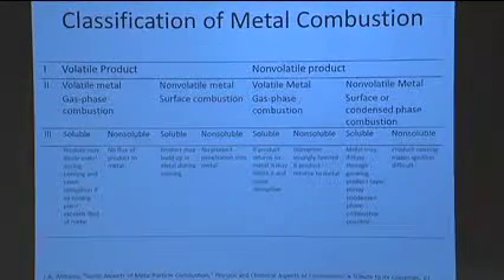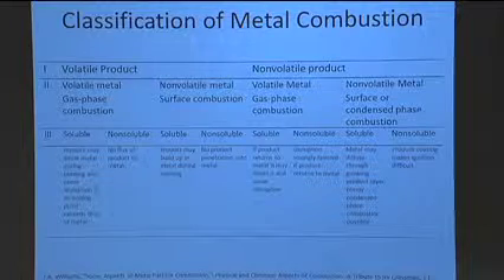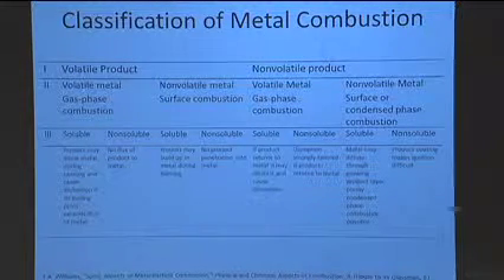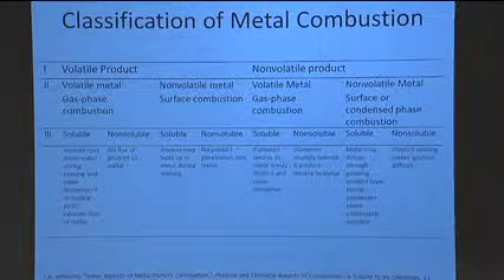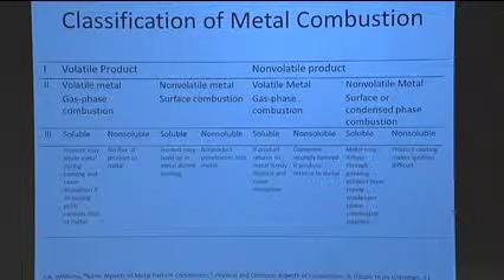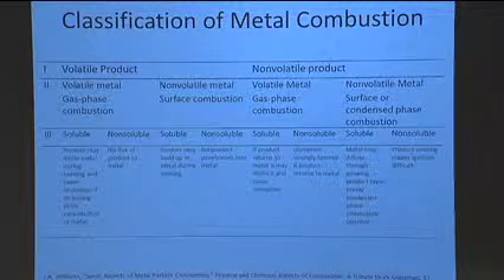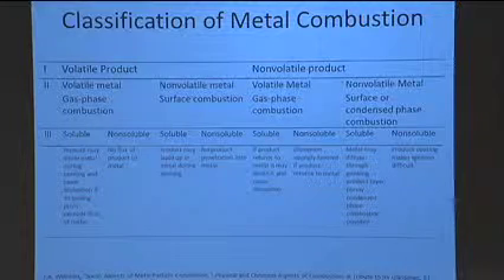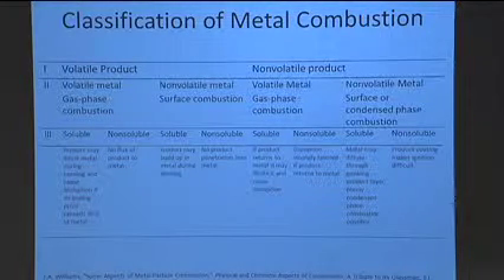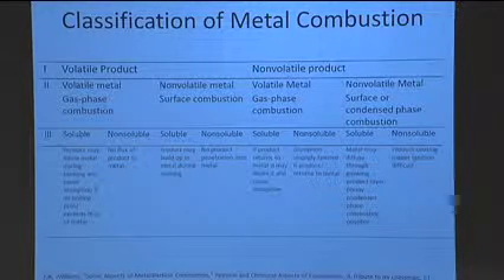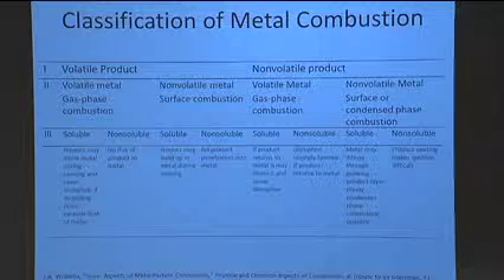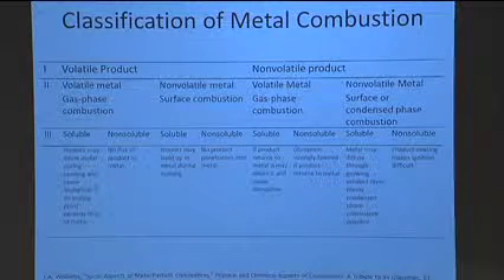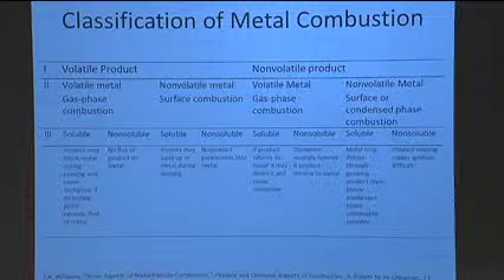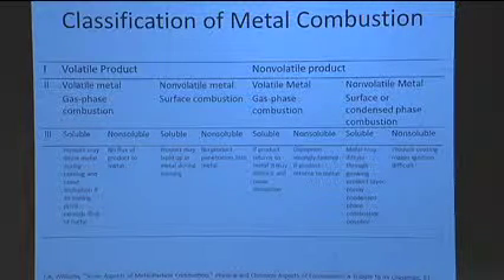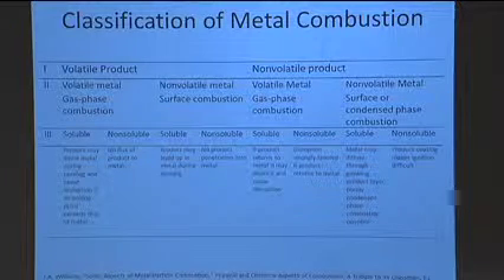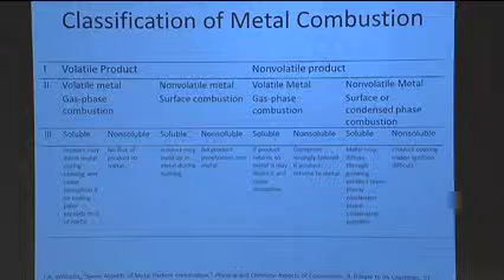So for example, if I look at this first column here, I have a volatile product, I have a volatile fuel. This would be how a hydrocarbon droplet would burn, right? I form gaseous CO2, water, and I end up vaporizing my fuel. If I come over here, I have a volatile product, but with the energetics, I can't vaporize the original fuel. I end up having something like a carbon particle, where the carbon particle doesn't vaporize, but it forms carbon dioxide as a final product. Over here, I have my non-volatile product, but a volatile metal. This would be like the aluminum particles that I just mentioned, or magnesium. And if I look over here, in this case, I have both a non-volatile product and metal. So in this case, I'm going to have the product being formed directly on the surface. This might be something like hafnium, how it might burn.